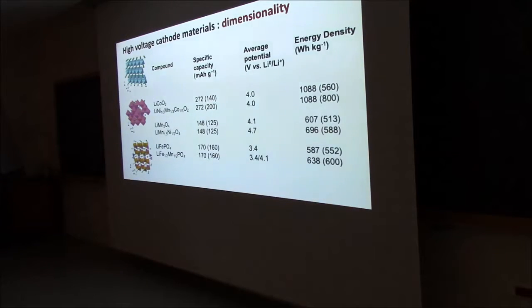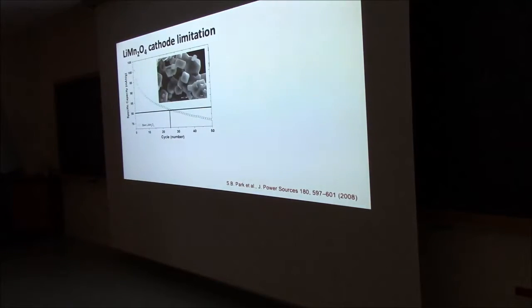Now lithium manganese oxide, the spinel, it has some problems. So people have been studying this for a long time, and if you make a battery out of it in more bulk processing, what happens if you make it in combination with such a liquid electrolyte and graphite anode, you cycle it a couple of times and the capacity drops dramatically in, let's say, 25 cycles.